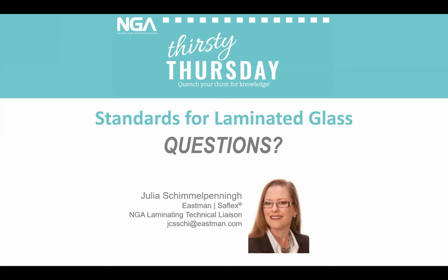Okay. How much can moisture contact along an exposed edge weaken the laminate and interlayer to a point where it can delaminate? So depending on the formulation of the interlayers, some are very hydrophilic, meaning they pick up moisture very easily and also get rid of moisture just as easily. But the effective moisture on all interlayers, they do pick up moisture. The amount that they pick up and the rate that it picks up moisture varies. And in some cases, it's not typically just moisture that causes a delamination. It usually at the edge, it is a combination of factors.